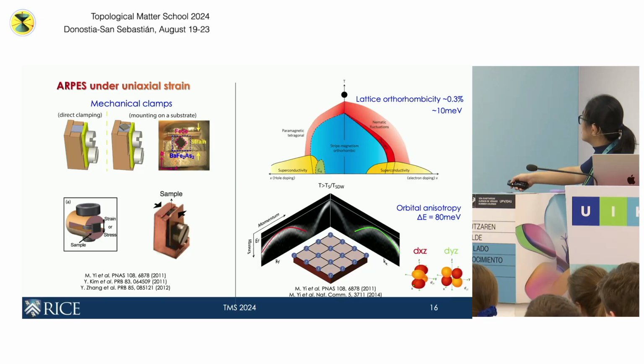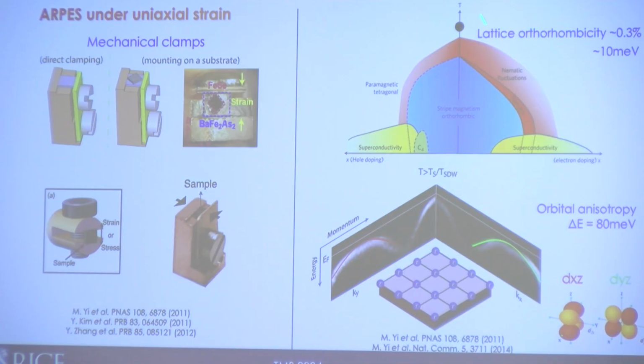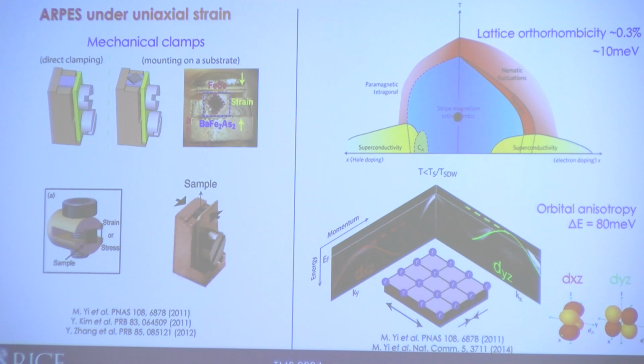So basically, you can measure the band dispersions along the orthogonal directions. In the C4 phase, these actually represent the XZ and YZ orbitals, and they are degenerate. And then if you go into the nematic phase, you can see that they actually shift anisotropically. And the important thing is that the energy scale associated with the symmetry breaking in the orbital degree of freedom is quite large. It's 80 milli-electron-volts. You can compare this to the amount of energy difference you can actually get by only considering the lattice orthorhombicity. This is almost an order of magnitude larger than this. So this suggests that this phenomenon of the orbital anisotropy cannot really be driven by the lattice degree of freedom, but it's really one of the driving forces of this order.